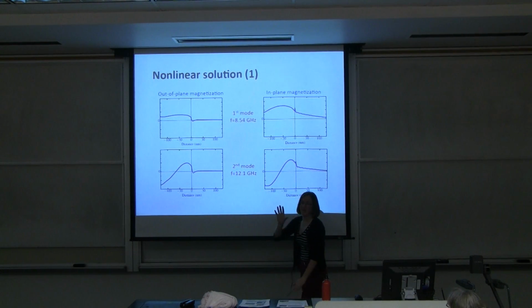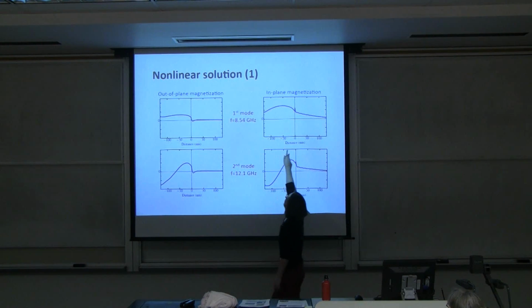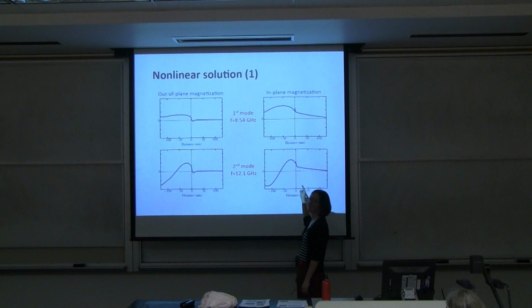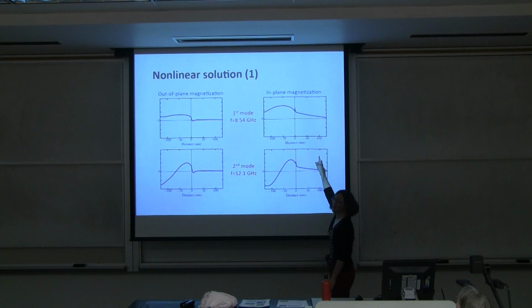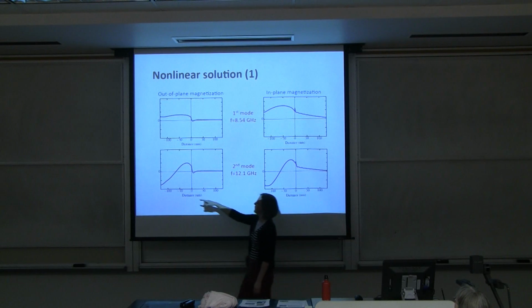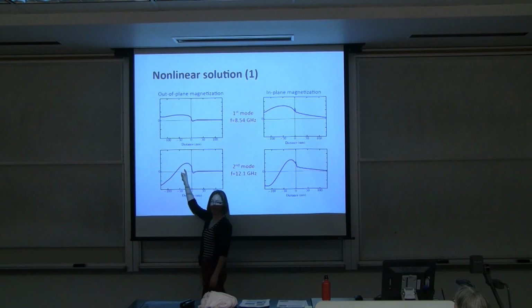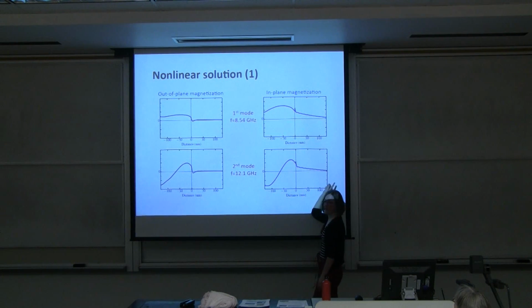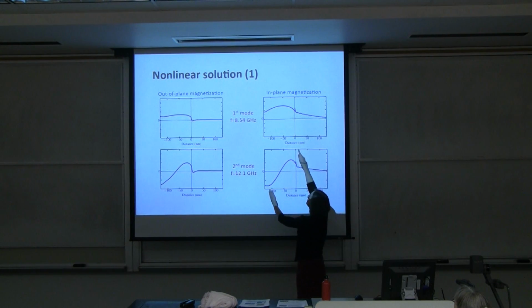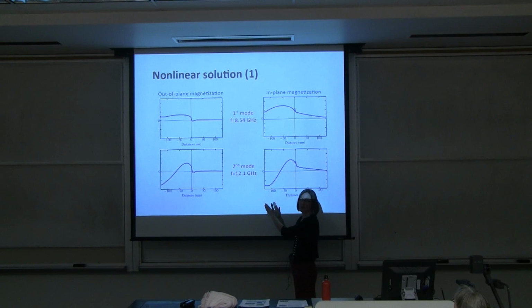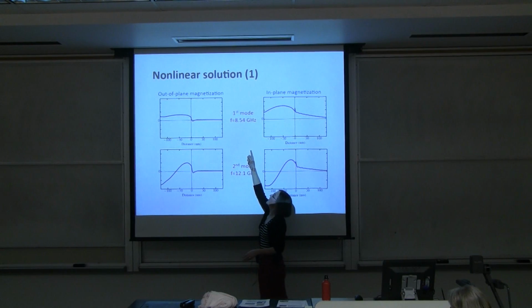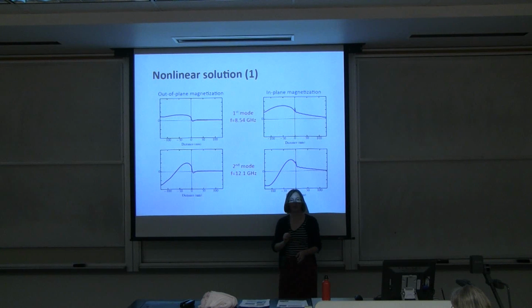So when we solve our nonlinear equation, we get that this is our first mode. So you can see it's mainly localised in the nickel iron and not so much in the cobalt iron. This is our second mode. Again, it's localised in the nickel iron, all right, and not so much in the cobalt iron. And you can also see going from the first to the second, we have a shorter wavelength and therefore a higher frequency. And the frequencies of these first two modes are 8.5 and 12.1 gigahertz, all right, which, as I said to you, was the typical frequency of these magnetic materials. So we think we're on the right track getting those sorts of numbers out.